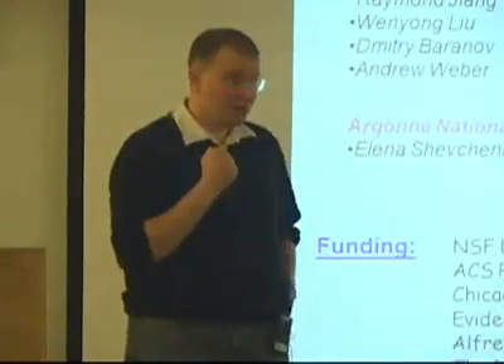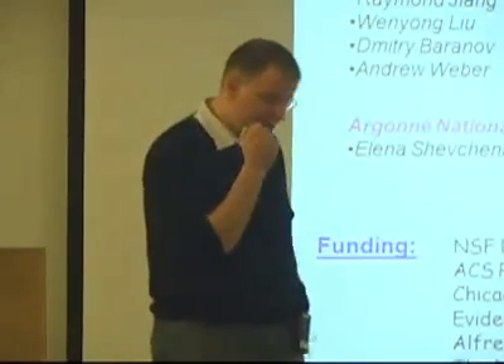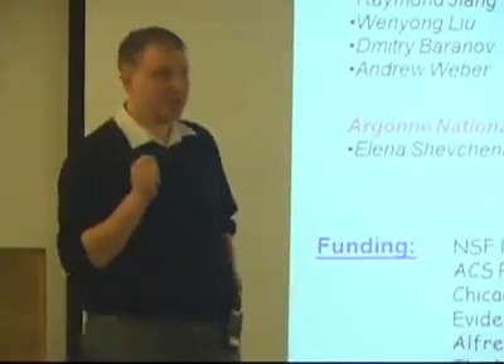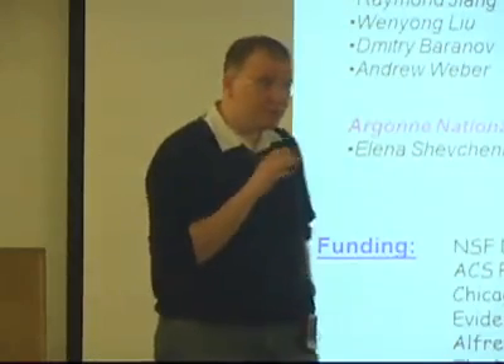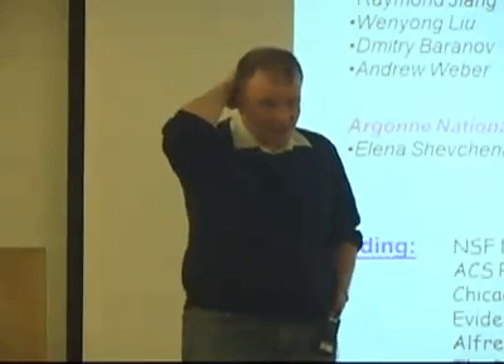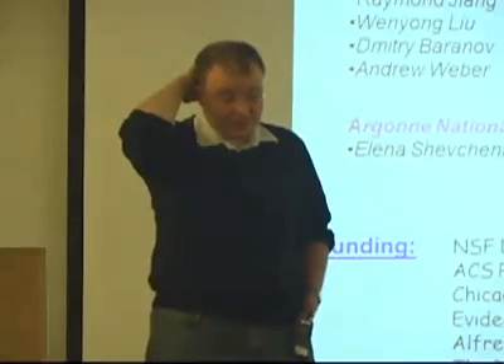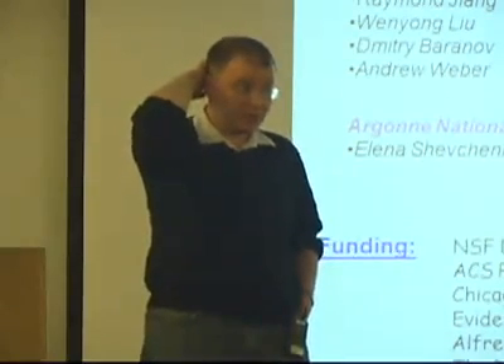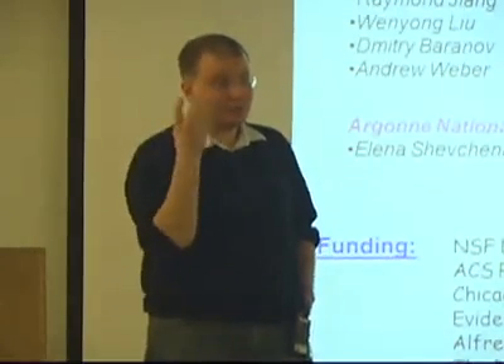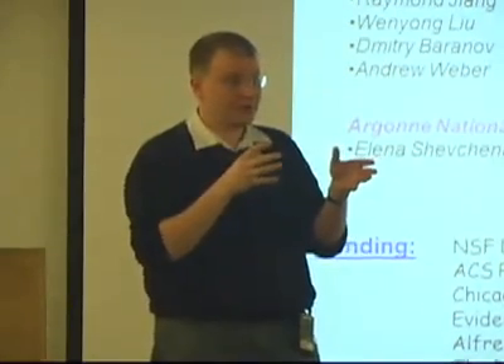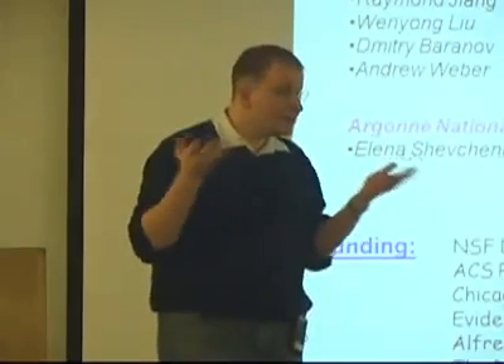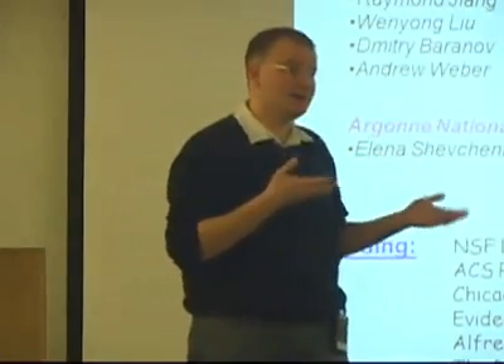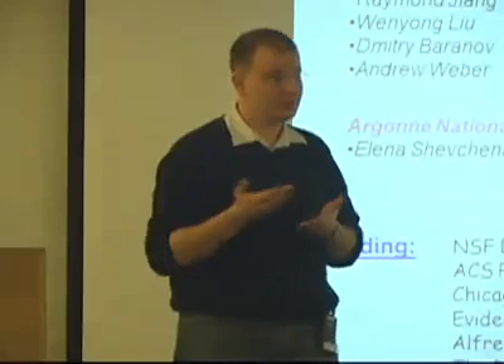Carrier mobility is definitely enhanced by many orders of magnitude. Carrier concentration is a bit more difficult parameter. We describe it as the threshold voltage for a field effect transistor, and it depends. We found that it depends on the heat treatment and on the amount of ligands we put at the surface. We can control it. So you can have either high dark current or low dark current. That's how it works.